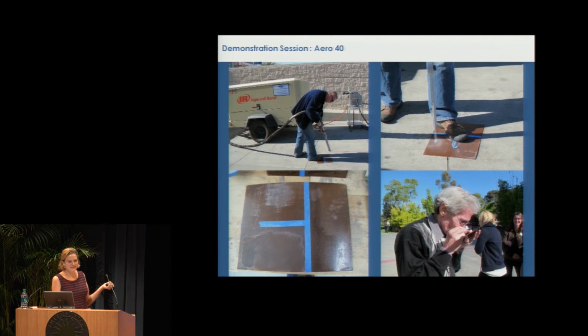And then our scientist, Frank Preußer, looked at it with his little loupe to see how much corrosion product, because of course you also remove iron oxide corrosion product, was removed, and it seemed that it was pretty okay. Back then they used 100 psi to blast that, and they were really close to the layer. So that was a really harsh way of cleaning the layer. But all in all, we were convinced of the pellet blasting.